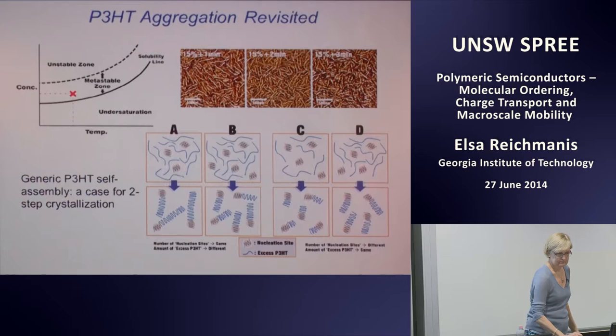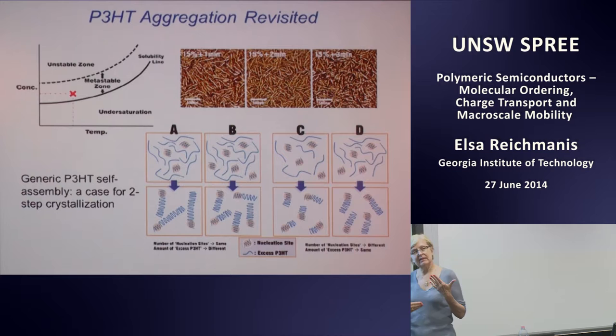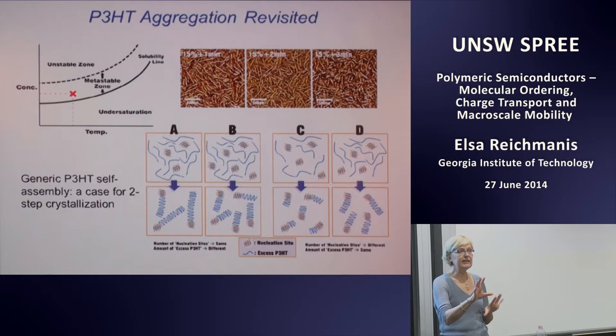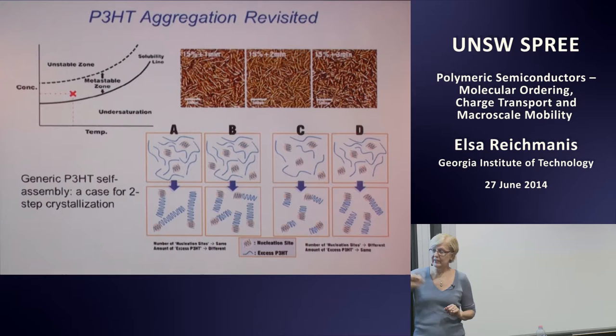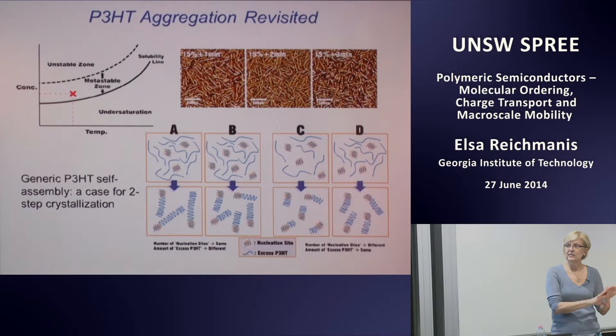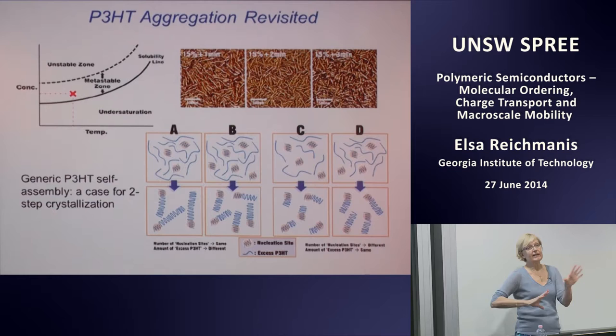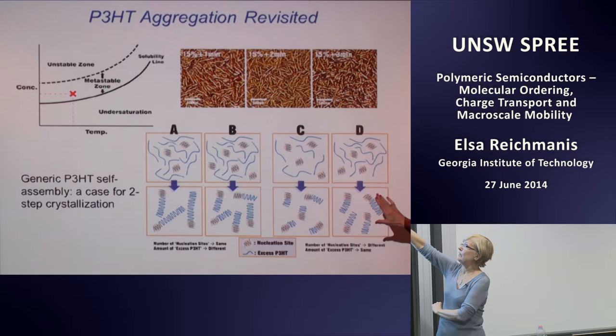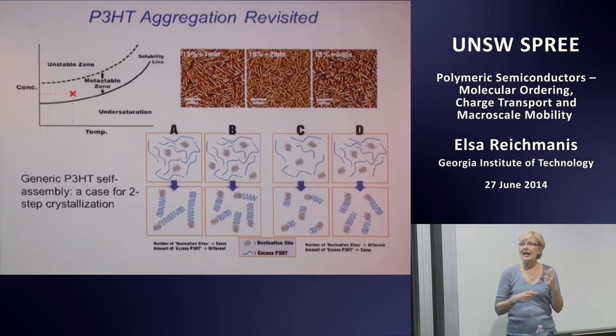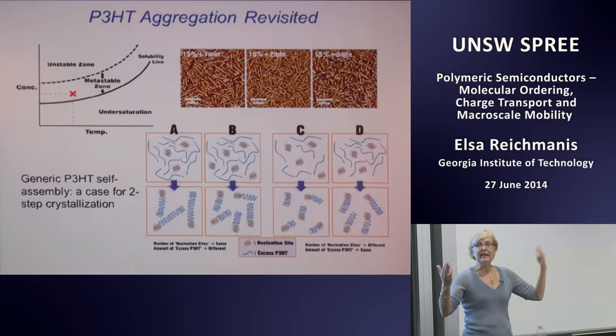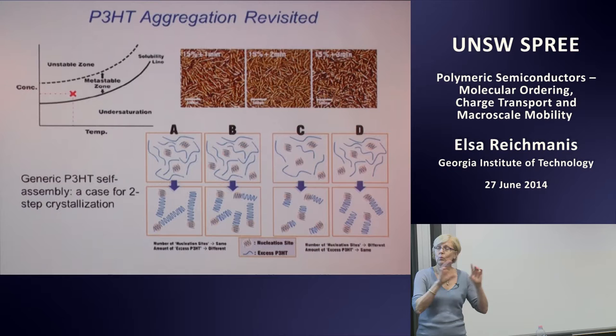So we've started looking at the aggregation phenomena of P3HT in solution. And from some studies that we've been doing, we've started combining processes where, in one case that I've shown here, we've been looking at adding a non-solvent to a good solvent P3HT mixture. And after adding the non-solvent, then doing an ultrasonication treatment. And again, what we find is that through this combined process, we can actually optimize the length of the nanofibers that are formed in the P3HT film. And as we optimize that length, we also increase crystallinity and in addition improve the charge transport characteristics.